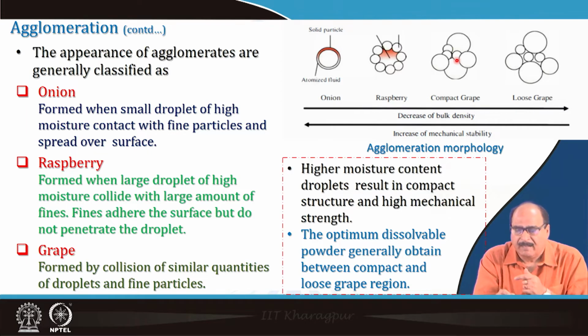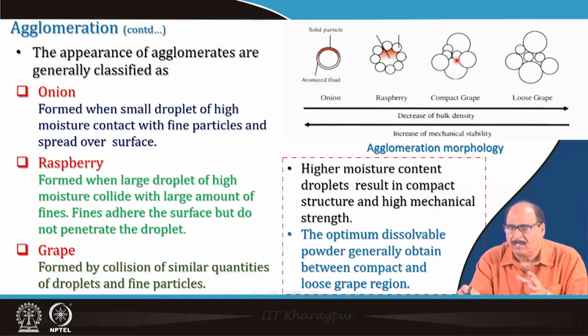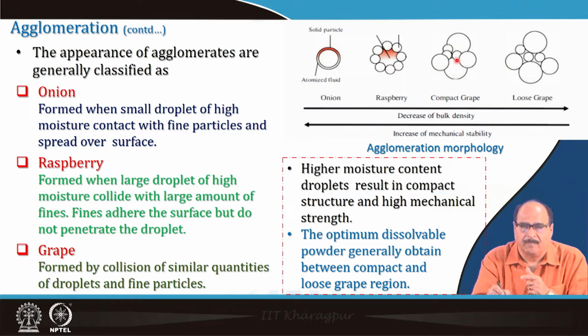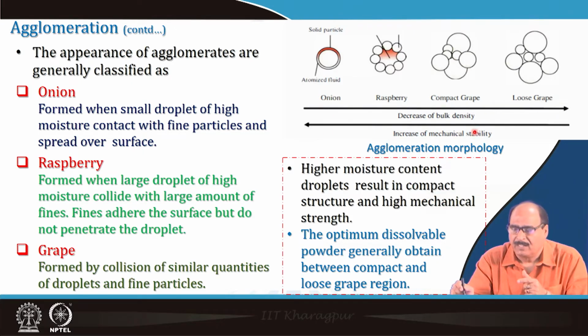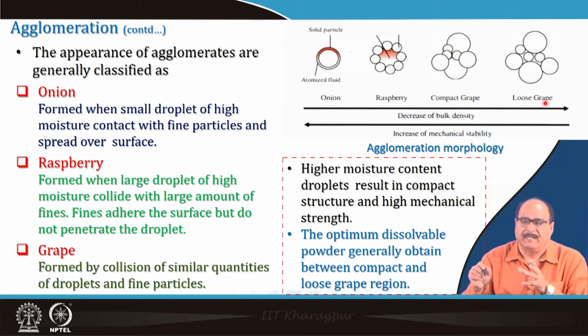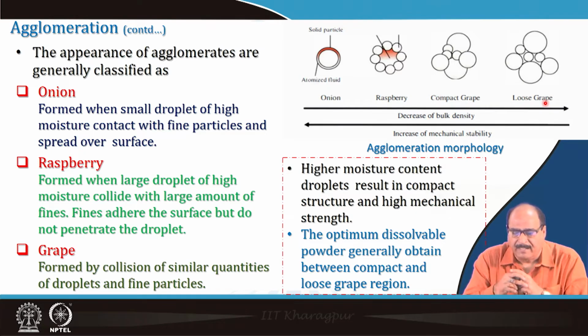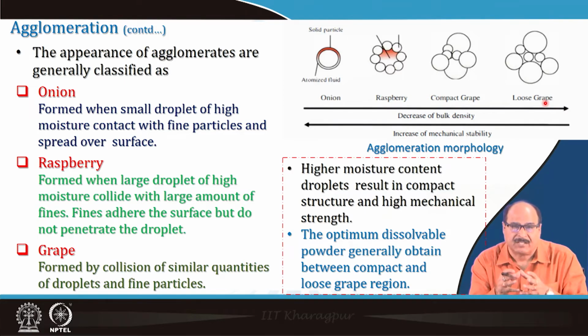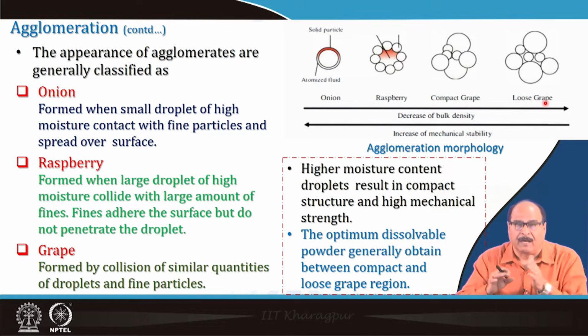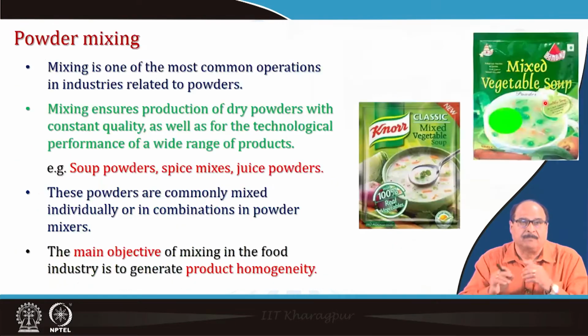Normally, you see that onions have the maximum bulk density, whereas the loose grapes have the minimum bulk density. For mechanical stability, onions have the highest, whereas the loose grapes have the lowest, and raspberry and compact grapes are in between. So, higher moisture content droplets result in a compact structure and high mechanical strength. The optimum dissolvable powder is generally obtained between the compact and loose grape regions.